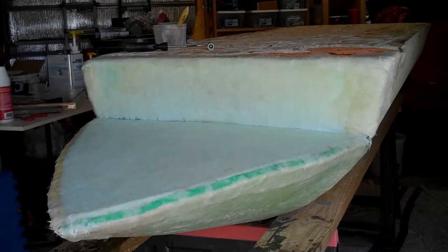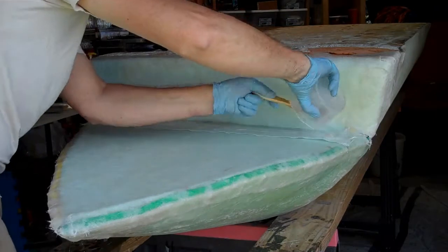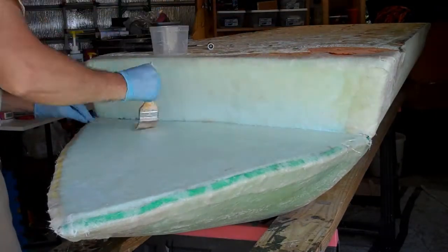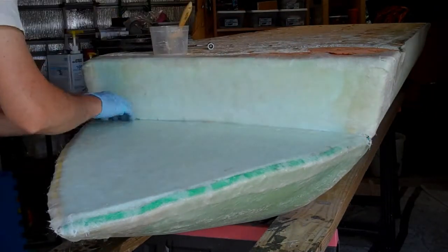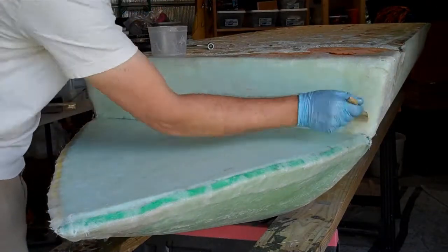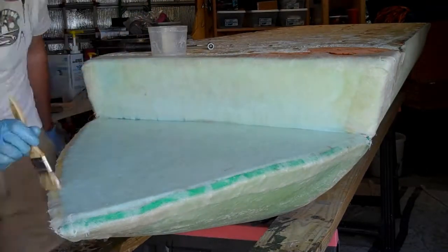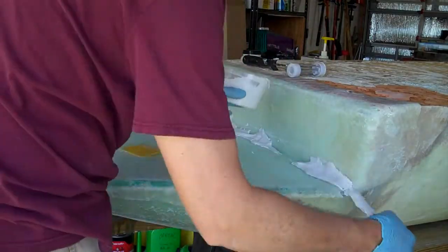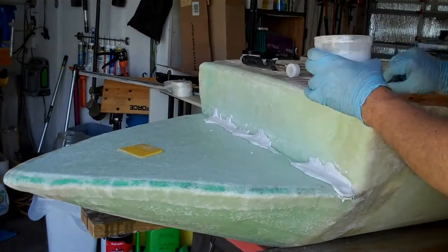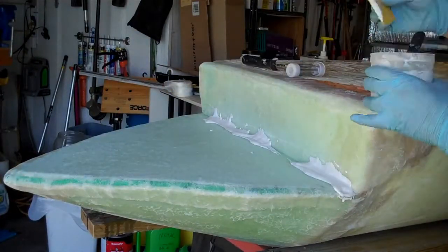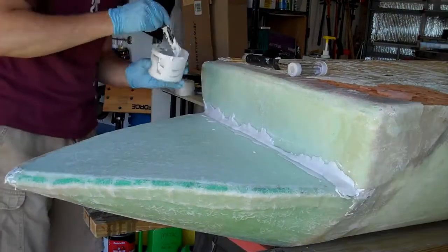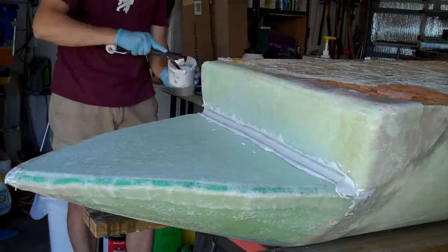The gap between the front and top surfaces is not a straight line, so I have to cut the mat to allow it to lay flat. To cover and join this cut, I have a thin piece of woven fiberglass tape that I wet out and lay over the two pieces. I use glass bead microballoon epoxy paste to fill in lots of holes and fillet the sharp edge at this stage, so check out my mini video on that topic to get more details.